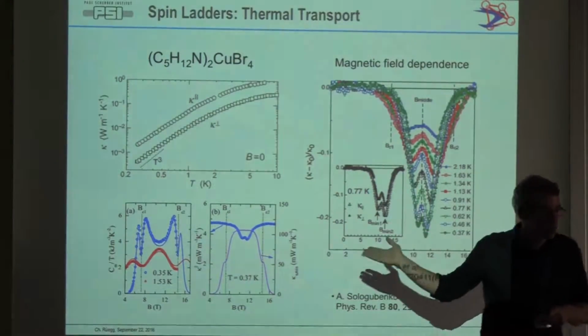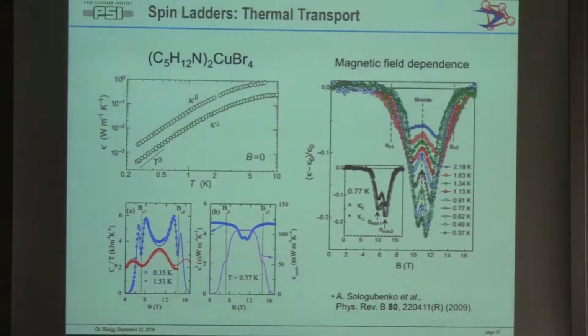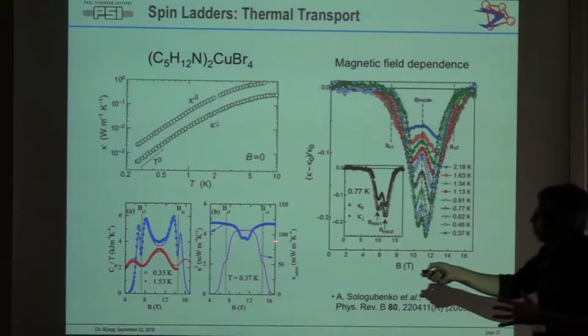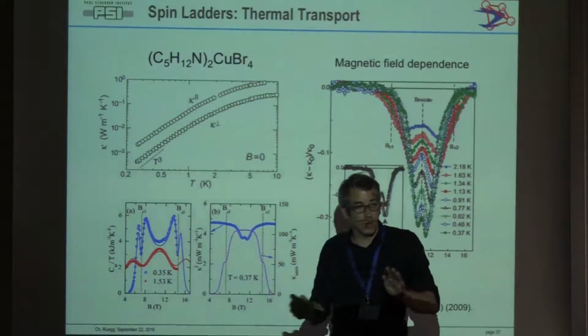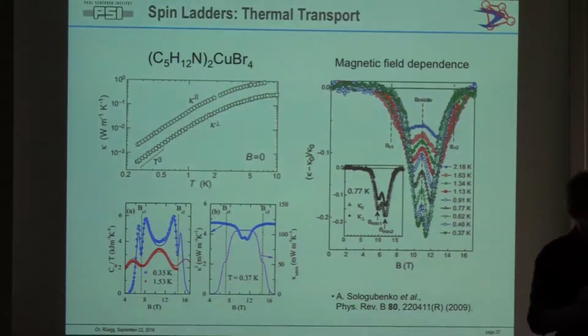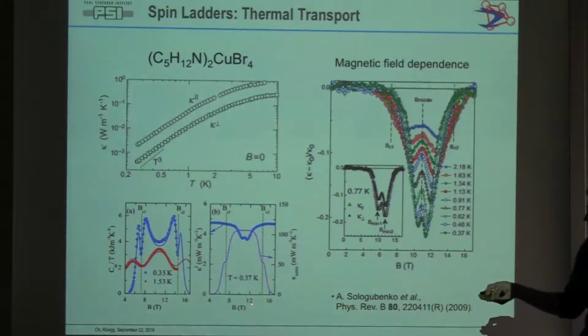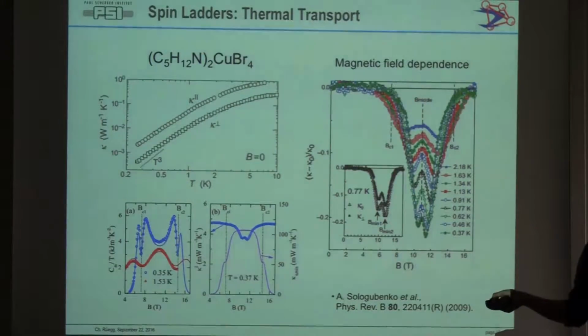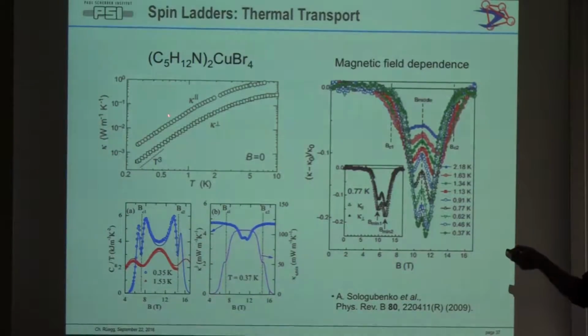So I think the picture is just completely wrong here. At low temperature, as a function of temperature, the fact that there is a strong conductance in the limit where there are no spin excitations tells us that this conductance is done with some... Yes, but this is the total conductance. Of course, in this case you don't have a separation in energy scales between the spinons and the phonons. So if you measure at 400 millikelvin, you still get a finite contribution from the phonons, and it can be clearly dominant.